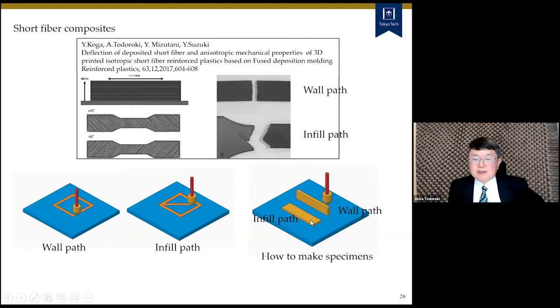So if we print the specimen like this, this is a print bed, this has an infill path. So the test result will become the plus minus 45 tensile test. But if we print the specimen like this, we can print a specimen only with the wall path. So all the print paths are along the tensile direction. So this has a very strong result, so we have to be very careful. We can easily print the specimen, but you can see that how to make the specimen is very important.